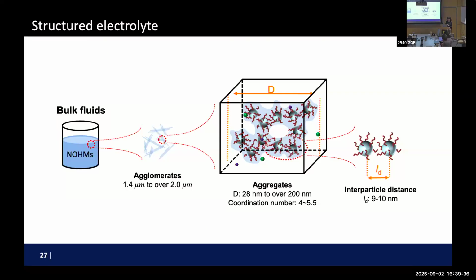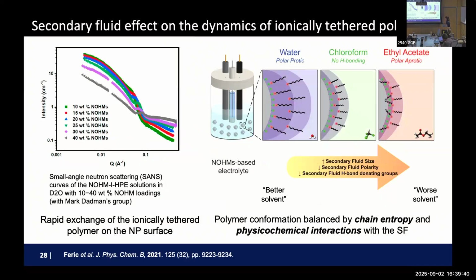And we even took it with Mark Dadmun, our friend at Oak Ridge National Lab. He did the SANS, which is the small angle neutron scattering. And what he also found was, we thought that all the polymers are really well tethered onto the nanoparticle. That's what we thought, because when we do TGA, all these polymers degrade at the same temperature. So we thought we have a single type of polymer tethered onto nanoparticles. That's what we thought. But this SANS data basically showed there are two types of polymers.